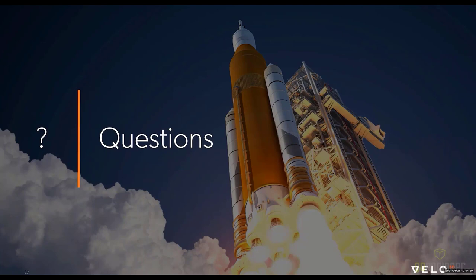All right. Do we have any design guides? Yes. We have the Velo3D design guides. We have a series of YouTube videos as well where we discuss these. Because we don't run into recoater clash issues, as we have a non-contact recoater, and we're able to print at much lower angles than 45 degrees, generally down to 0 to 10 degrees based on the geometry, the residual stress and the structure stability plays a greater role. So we have several plots out there of minimum angle as a function of geometry shape. And that helps design engineers and manufacturing engineers alike to really get the optimal solution from Velo3D's technology.